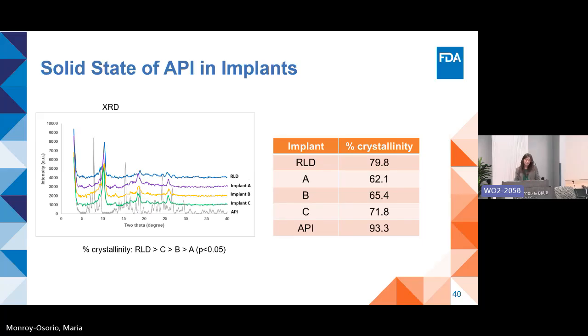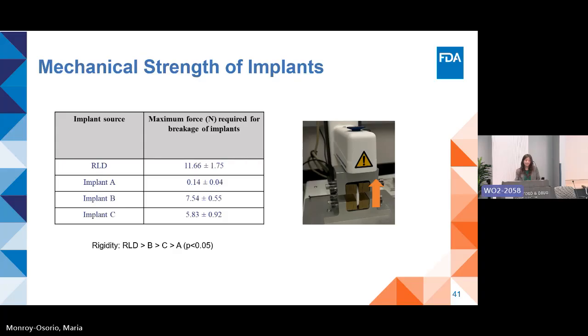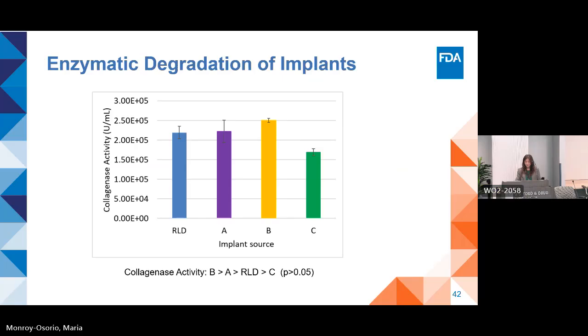Then we investigated the solid state API in the implants. The results show that the percent crystallinity in the RLD was significantly higher compared to implant C, implant B, and implant A in the descending order. And then we investigated the mechanical strength of the implants. The results show that, again, the RLD shows significantly higher rigidity compared to implant B, implant C, and implant A in descending order.